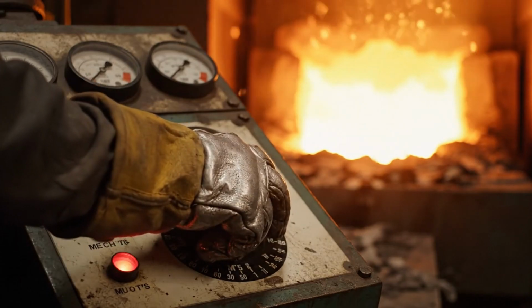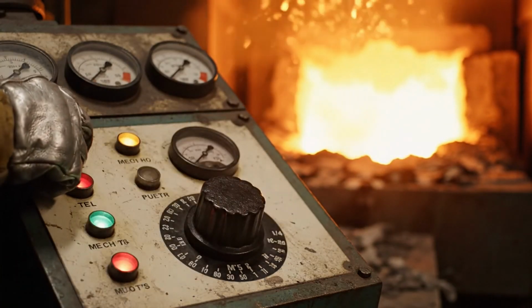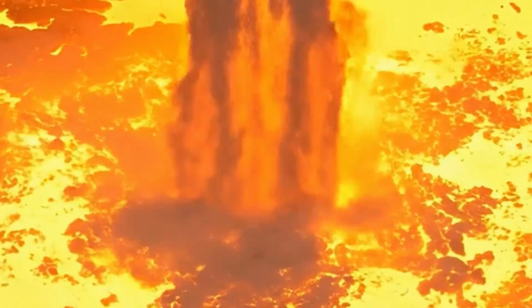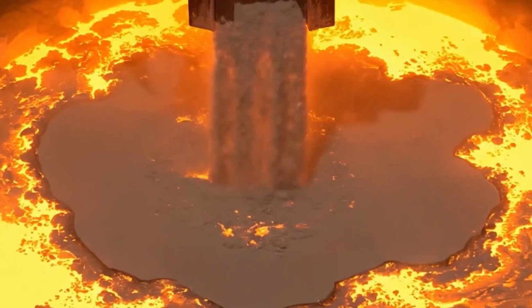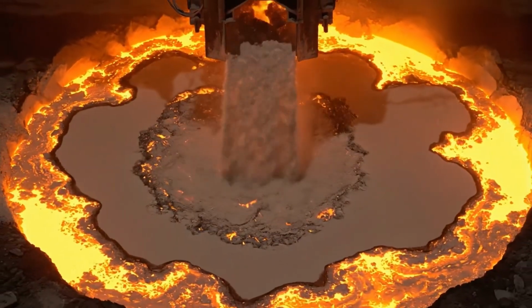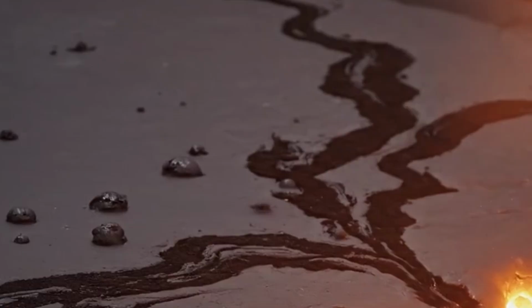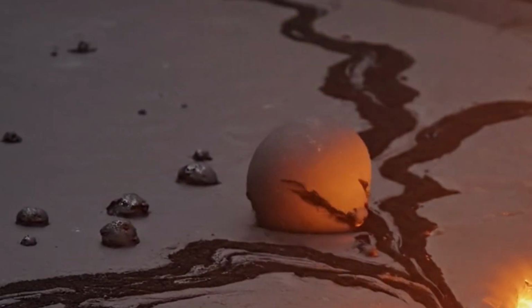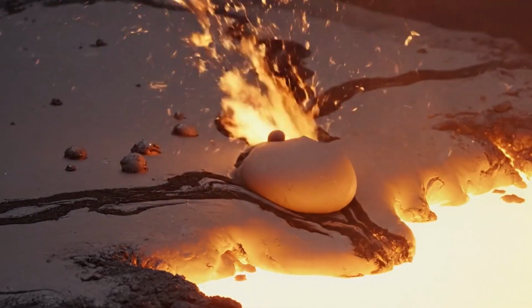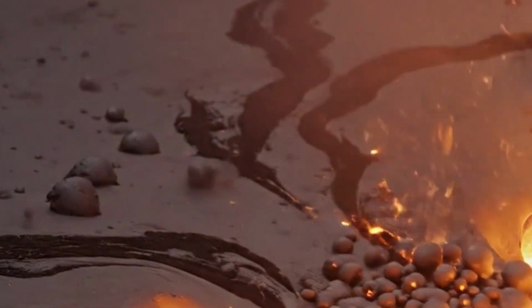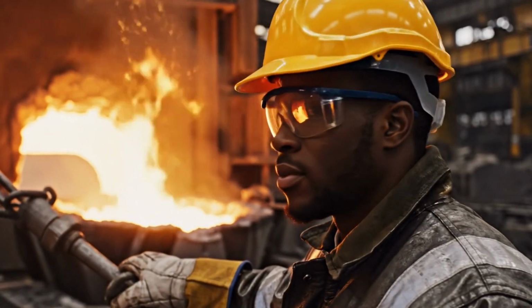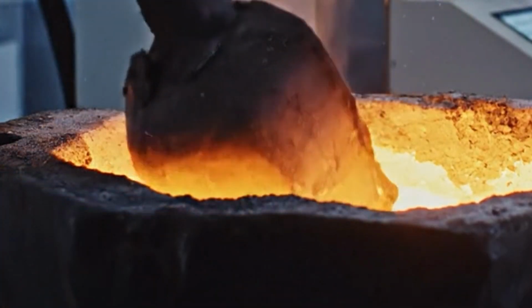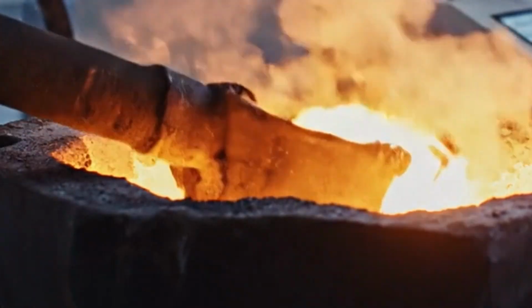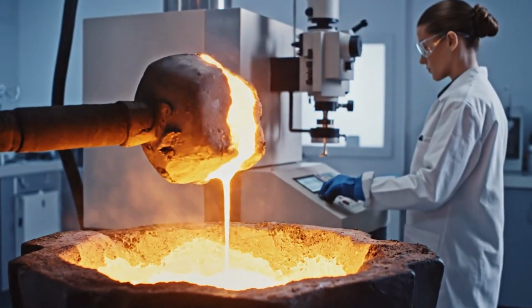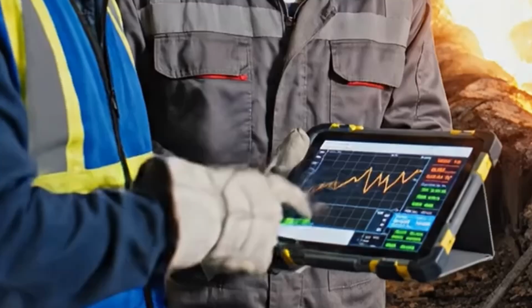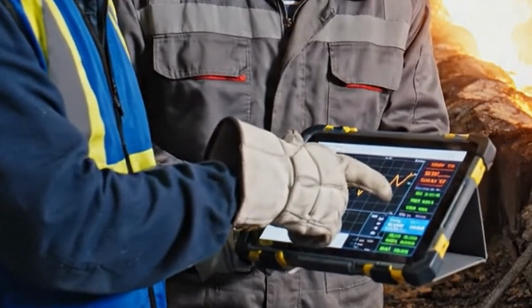This control is essential. A brake disc operates under severe thermal cycles. If the material doesn't have the appropriate microstructure, it can crack, deform, or wear unevenly. When the molten metal reaches the desired composition, it is poured. The molten metal flows into a large lined ladle capable of maintaining it at still extreme temperatures. There, final adjustments such as deoxidation can be made to reduce the presence of dissolved gases that could later cause internal defects. The quality of the liquid metal is crucial.